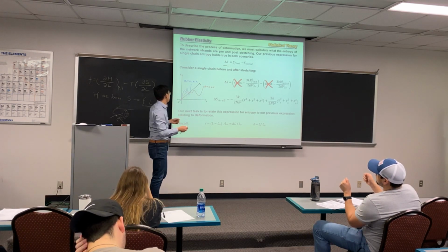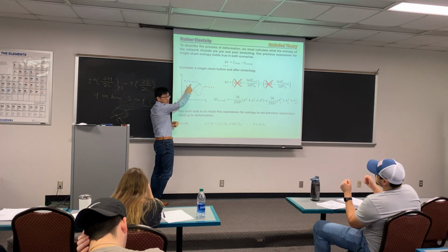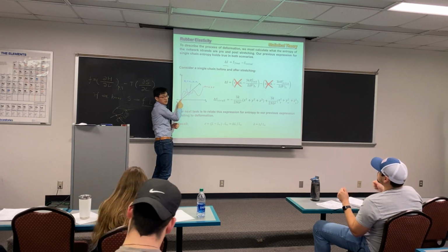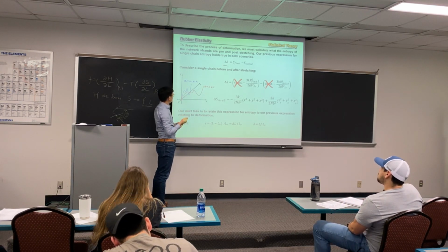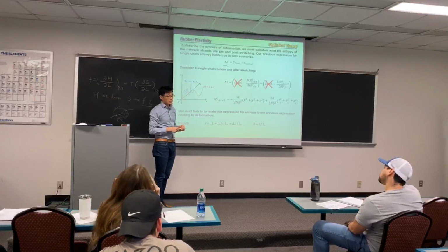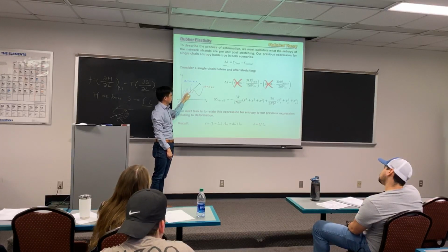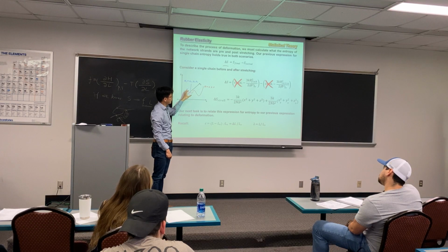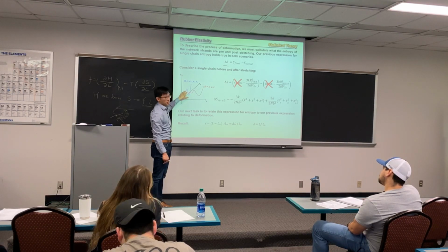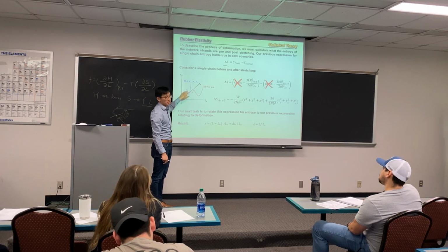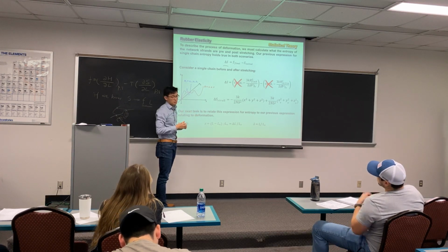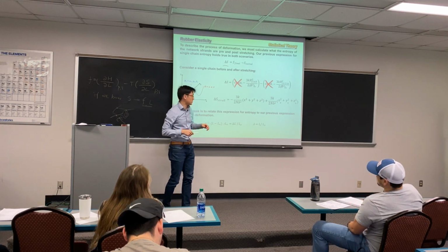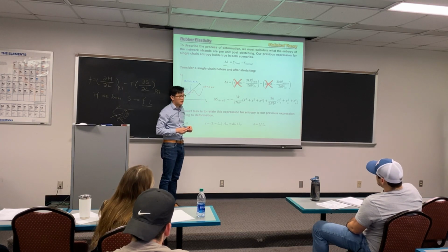Then think about you pulling the one chain while I'm holding the chain at the origin. Now it's being deformed to be longer than what it's supposed to be. And we know R0, if we know the segments, we can actually show that R squared will be nb squared. But we can say, if we pull it to double that length, what would be the entropy change? We can calculate based on this.